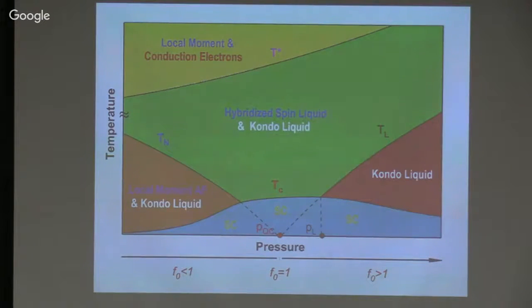Not shown there is one more fascinating aspect of heavy electrons. That's quantum critical behavior, because you can see that in the transport experiments. And what it does is to cut off the scaling behavior that's seen in the Kondo liquid. It shows a very different temperature dependence, and you can begin to sort out in detail the nature of the quantum critical regime, out of which, in fact, in general, superconductivity arises.